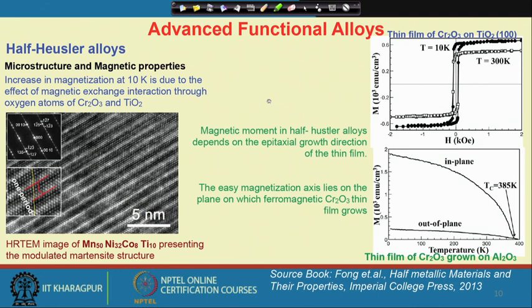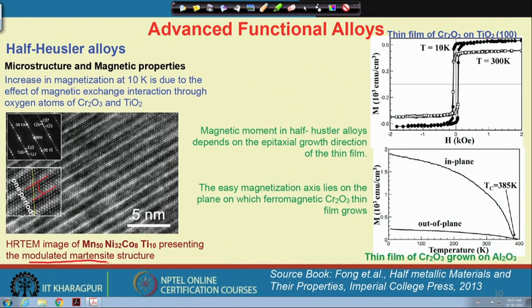Now, when we talk about these half Heusler alloys, there are some structural features. Usually these have a microstructure content, mostly martensitic structures, and these martensitic structures are highly twinned. I show you one example of such a structure, a modulated martensitic structure. It basically means that layers of different martensite coexist together, and these are the typical twins in a martensite. You can see one such periodicity here, and this is the diffraction pattern, from which we can also measure how many weak spots are present until the sharp spot. So, let us say this is a 5M modulated microstructure.